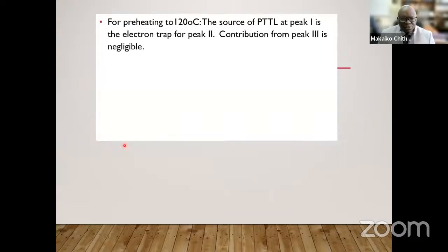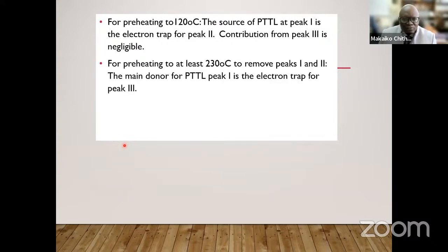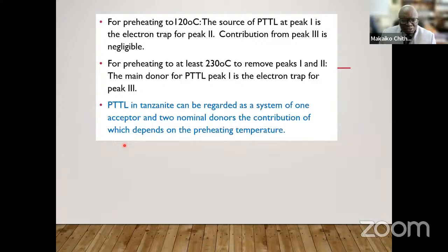So this summarizes what I've just said. The source of phototransfer at peak 1 is the electron trap for peak 2, and once peak 2 has been removed, the main donor becomes the electron trap for peak 3. So these are qualitative conclusions we draw from the experimental results.